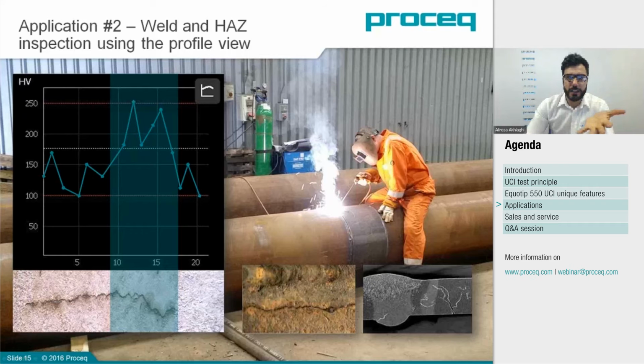This information is basically telling us that this particular area has been exposed to heat potentially for a longer period of time and over certain intervals during perhaps the manufacturing, welding process, heat treatment, and so on. And these heat treatments over and over have caused it to become harder, therefore more brittle. And let's assume that this was a pipe, the pipe has been pressurized, it has failed, and the crack has appeared. So by utilizing the profile view with the UCI probe in Equotip 550, you'll be able to simply and easily plot this profile trend of hardness and identify the problematic areas and perhaps even prevent it before it leads to a failure.